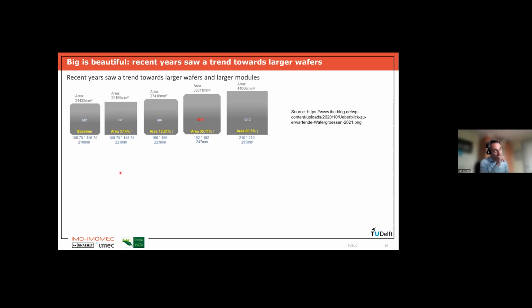But then there were two reasons why the wafer size has increased. There have been quite some improvements in the whole process that I just explained, so that it was possible to make larger wafers. And these larger ingots typically also reduce the cost. So it's really from a cost perspective that people have started making larger wafers. And you see that the sizes now being used go from the original size, 156 millimeter, all the way to square wafers, which we call G12, of 210 times 210 millimeter. The area of such a wafer is 80% larger than the original wafers that we used to use.